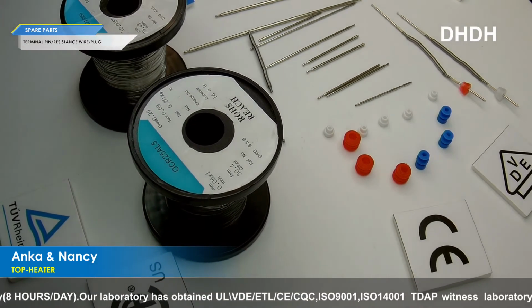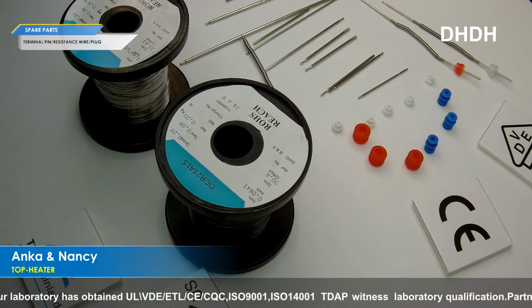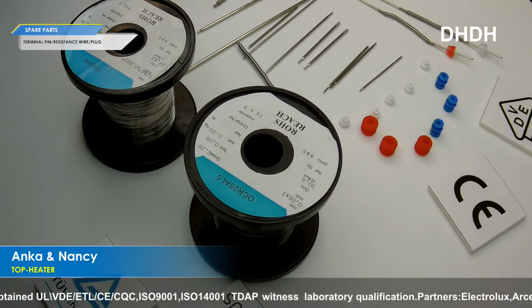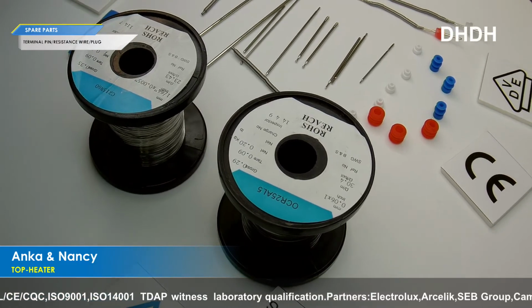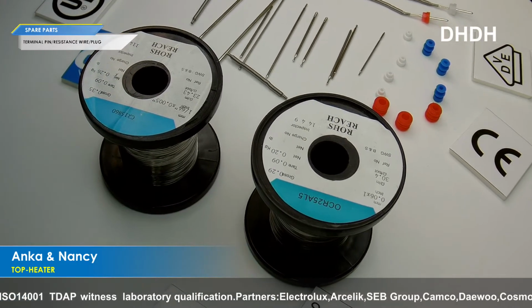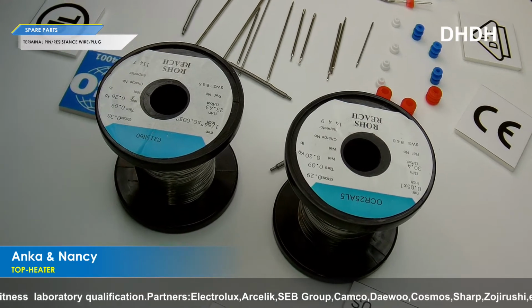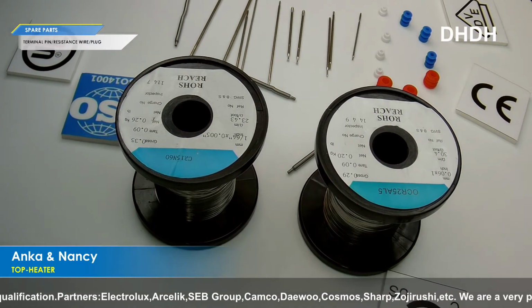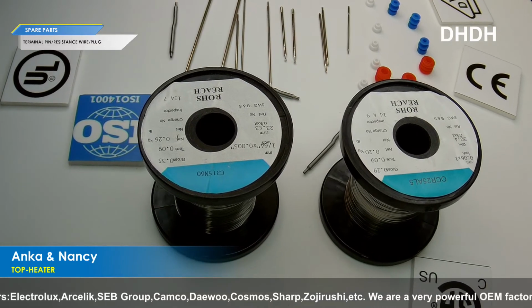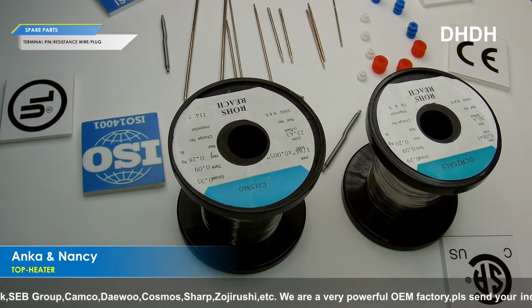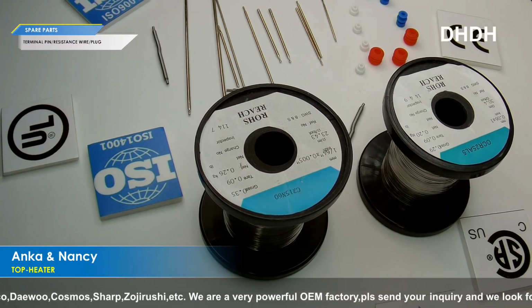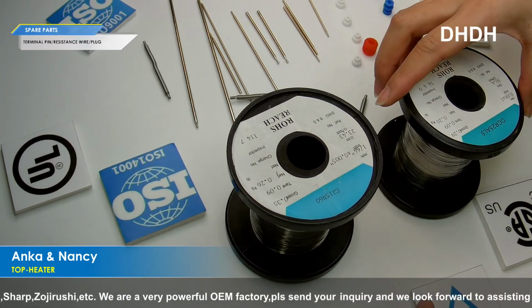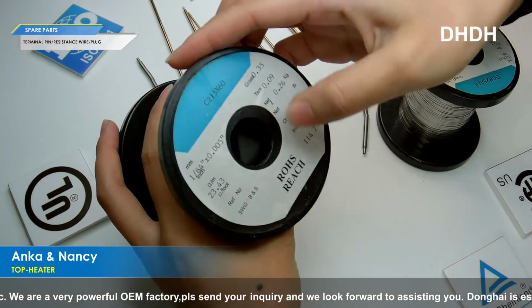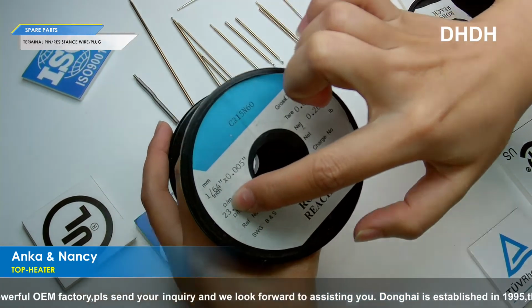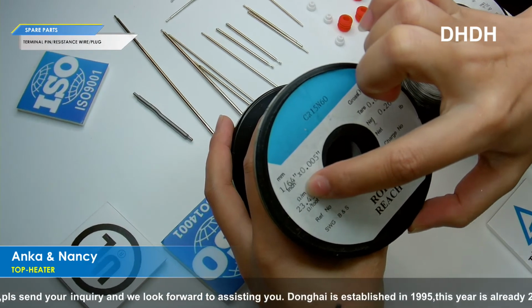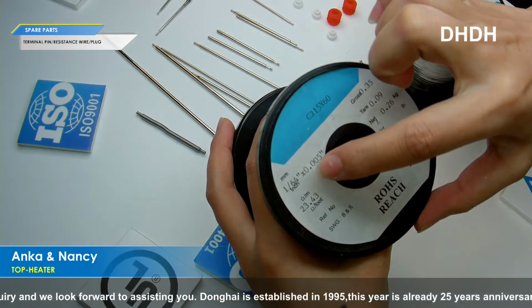And the resistant wire diameter we can make is from 0.1 millimeter to 1.1 millimeter. The tolerance of the meter resistance is plus minus 3%, and the international standard is actually plus minus 5%. It means that our meter resistance is more precise. Now, from the sample, you can see the meter resistance. For this sample, it is 23.43 ohm.